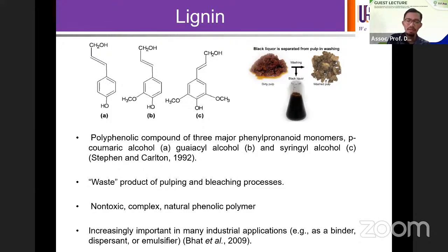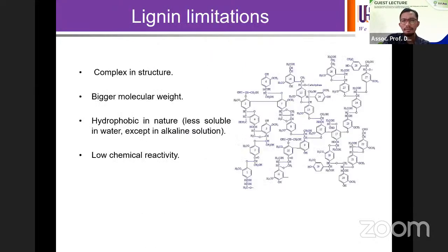As I mentioned, during the pulping process, if you want to produce paper, they will treat the wood and use chemicals. They will take the pulp, which later on is used to produce paper, but the black liquor they just discard. And this black liquor is very much rich with lignin. Lignin is also considered a non-toxic, complex-structured, natural phenolic polymer, and it has been increasingly important for many applications, such as binder, dispersant, and also emulsifier.